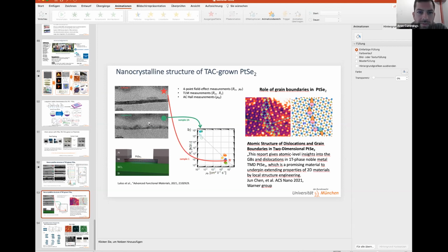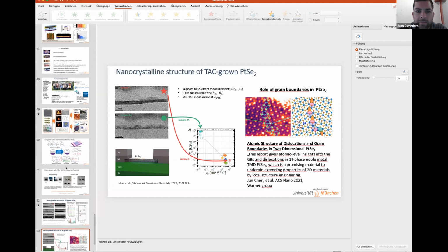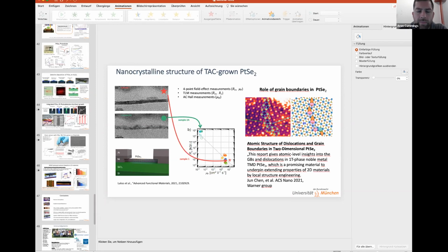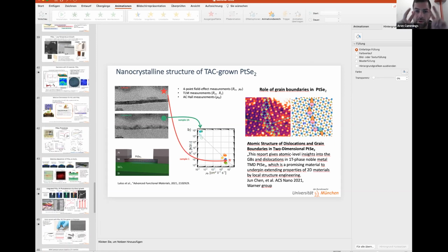We have one more question now from Christian Schaefer. For your microcavity MoS2 growth, how big are the substrates you use, and how good is it for large area homogeneity of these TMDs? The samples we use are a centimeter square in this case, in a tube furnace. I would believe that this process is not good for full wafer scale, because we already see differences over the sample region because of the microcavity.